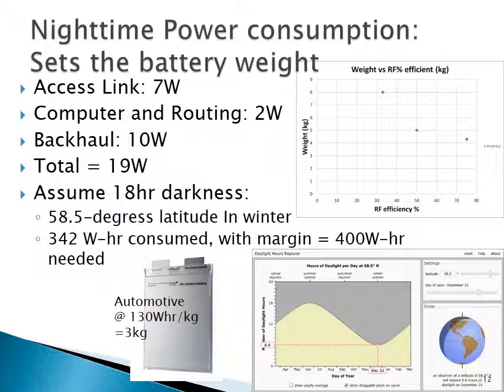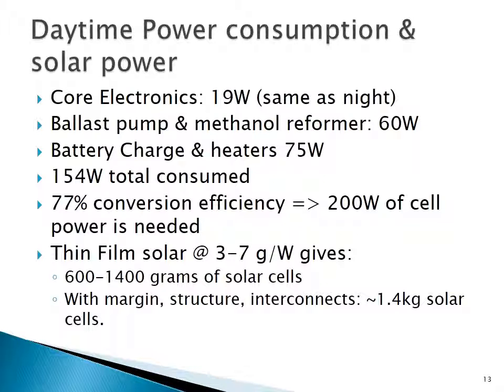That's nighttime operation, and nighttime, of course, varies depending on where you are in the world. If you need to be at high latitudes, then you've got to carry something like 400 watt-hours of batteries. I think the best pick is probably automotive-grade batteries because they have good cycle lives. A123 Systems, at least the automotive manufacturers are qualifying it for cycle life, and they're doing a good job. You can get commercial off-the-shelf batteries that have better power densities, but they're just not going to give you the same cycle life.